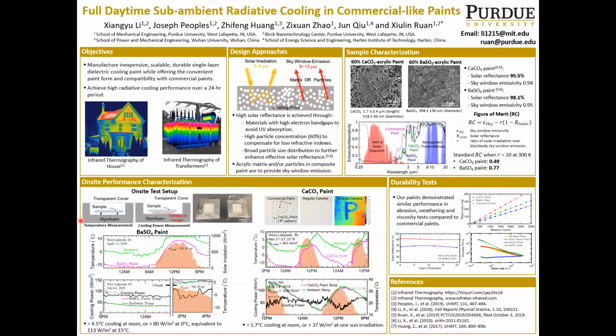We have two on-site test setups. The first one measures sample surface temperatures. The transparent PE cover is to reduce forced convection. The ambient temperature was measured at the shaded area. The second setup is to directly measure the cooling power by using a feedback heater, which maintains the surface temperature with the ambient. Both paints reach below ambient temperature under direct sunlight.